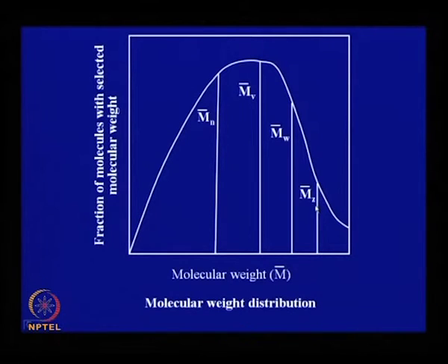This shows that Z average molecular weight is higher than weight average molecular weight, than viscosity average molecular weight, than number average molecular weight. So, number count gives you the determination of molecular weight of a polymer sample having low molecular weight species, low molecular weight polymers. For a high molecular weight sample, if you want to measure the molecular weight by number averaging technique, the result will be wrong, misleading.